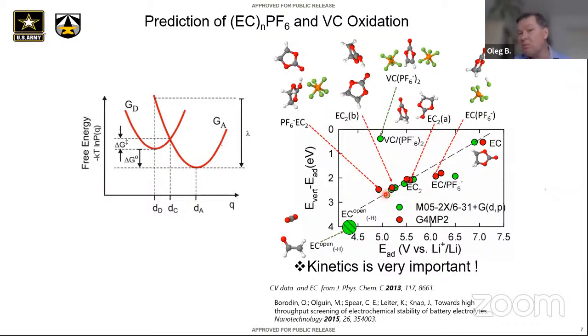And then I think, would it be possible that after removing this hydrogen, the EC decomposes by opening up this bond and creating CO2 and a radical? What's going to be this energy? This process is very, very downhill. If it overcomes this 0.8, or depending on the cluster, a 0.6 to 0.8 eV barrier, then the oxidation potential calculated relative to CO2 and the radical becomes 4.3 volts. So now that's within the voltage range of the majority of battery electrolytes.